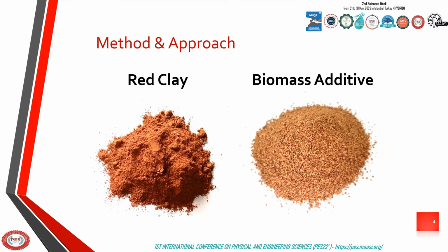In our first phase, I present you the materials and additives chosen to make the samples. The criterion for the choice of material is mainly the local availability. The red clay is presented as a material with high thermal performance. Unlike most building materials, clay can be used in its natural state. The clay was extracted from a red clay quarry. The powder of biomass additive used is obtained by grinding using a knife mill, then sieved.